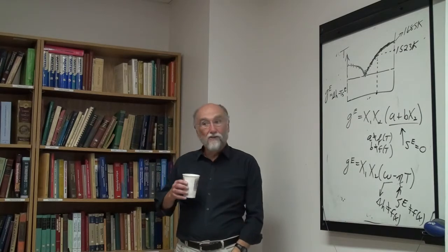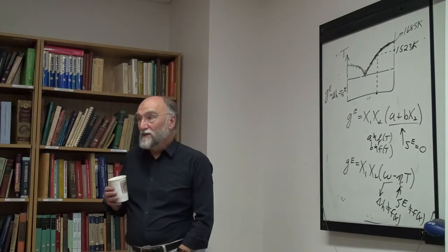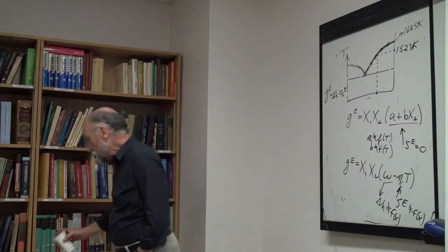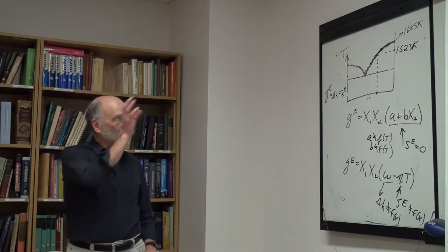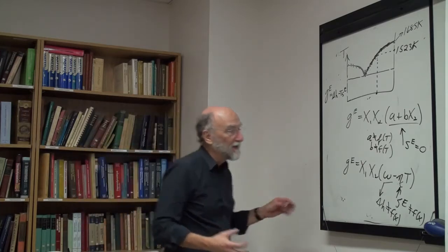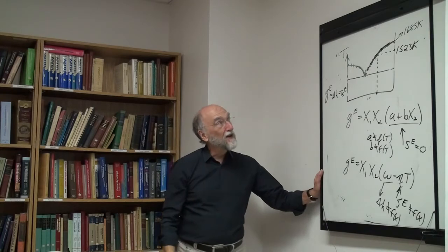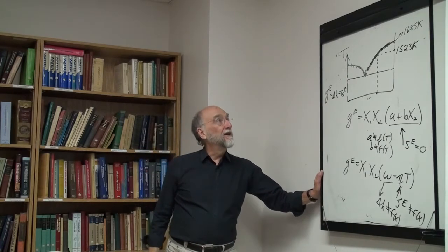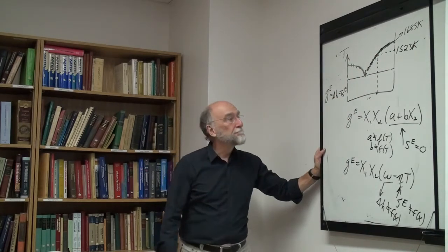But that's just experimental experience, that isn't actual thermodynamics. So this is why I say it's nice to be able to write out these equations and think about what you're really getting. So here you're not getting H and S, you're getting a non-isothermal, you're getting a GXS along a path, which is not a constant temperature.